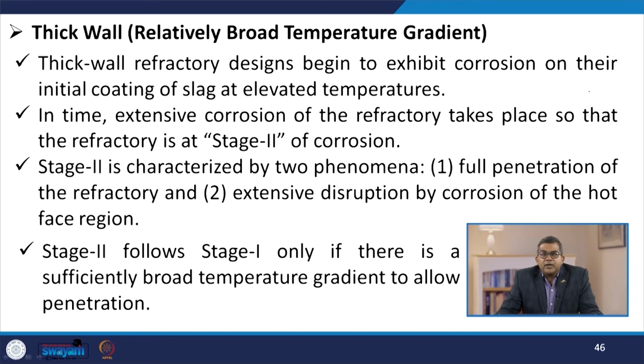Thick wall refractory designs begin to exhibit corrosion on their initial coating of slag at elevated temperature. In time, extensive corrosion of the refractory takes place, so that the refractory is at stage 2 of corrosion. Stage 2 is characterized by two phenomena. One is the full penetration of the refractory, and the second is the extensive disruption by corrosion of the hot face region. Stage 2 follows stage 1 only if there is a sufficiently broad temperature gradient to allow penetration.